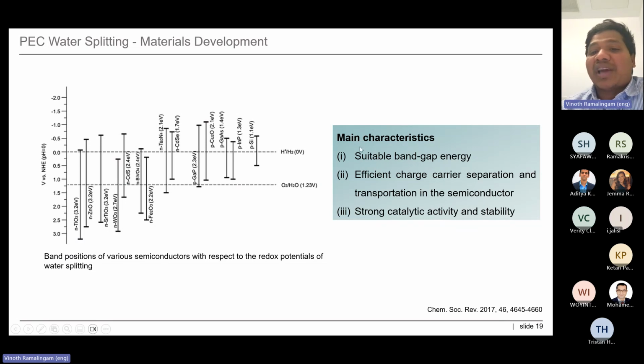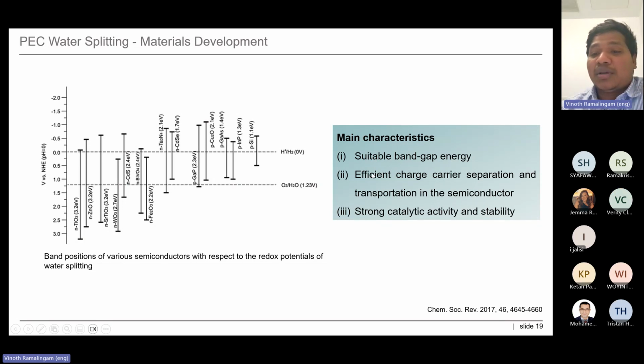We need to look at three main characteristics, particularly when choosing the photoelectrode materials. Again, the suitable band gap energy, and in most photoelectrodes, charge recombination is the major problem. Once it excites the charge carriers, because of the very short lifetime, the carriers tend to recombine so quickly. In that case, we will lose performance. So once excited, the charge carriers should be separated and transported to the interface to be involved in the reaction. And the last one is that it should have better catalytic activity as well as stability in the aqueous environment.